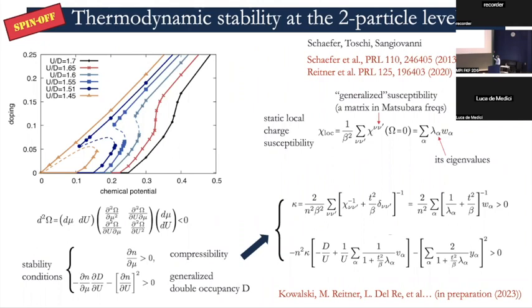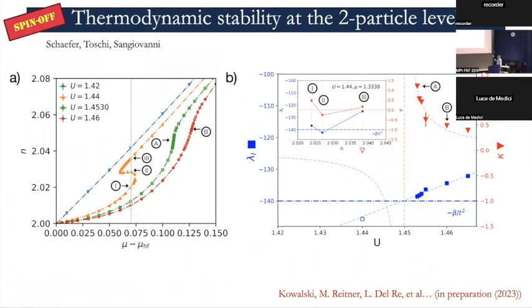So you can really see that if the eigenvalue reaches some negative value, set in the specific case of the Bethe lattice that we are analyzing by some number, but this would be a different number in more realistic models, then you have a divergence in either of these quantities. And indeed, here are the numerical results, done by Alexander Kowalski in QMC. Here you see the same curves that we have seen before, just at finite temperature. And if you follow the way the compressibility is diverging, coming from B to A and some intermediate curves, you will see that it diverges here. And this is the value of one of the leading eigenvalues of that matrix, which reaches this threshold. And indeed, it signals the divergence of the compressibility.